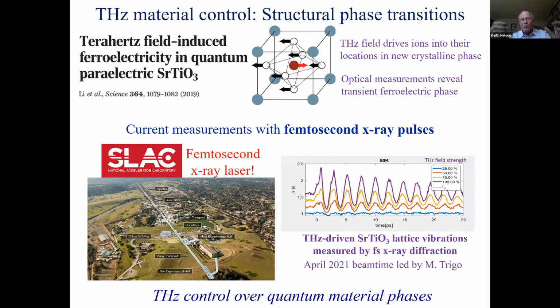But the point is that was produced by the terahertz fields. Very recently, in fact just this month, we've monitored that with femtosecond X-ray diffraction at a national lab facility, SLAC, near Stanford, where there's a femtosecond X-ray laser. By X-ray diffraction, right off the crystal lattice, you can see from the crystal structure that it's oscillating. There are crystal lattice vibrations driven by our terahertz pulse. This whole system, which is miles long, has an accelerator to produce the relativistic electrons that make this possible. That's what, in the previous example that I mentioned, we hope to see on a tabletop.